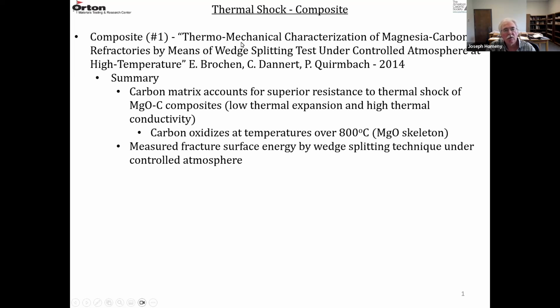The first one is thermomechanical characterization of magnesia carbon refractories by means of wedge splitting tests, under controlled atmospheres as a function of temperature. So this paper is just taking the wedge splitting test and adapting it to high temperatures.